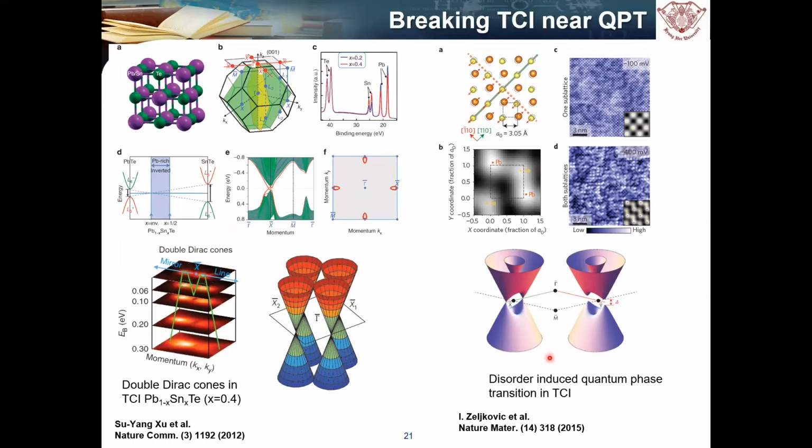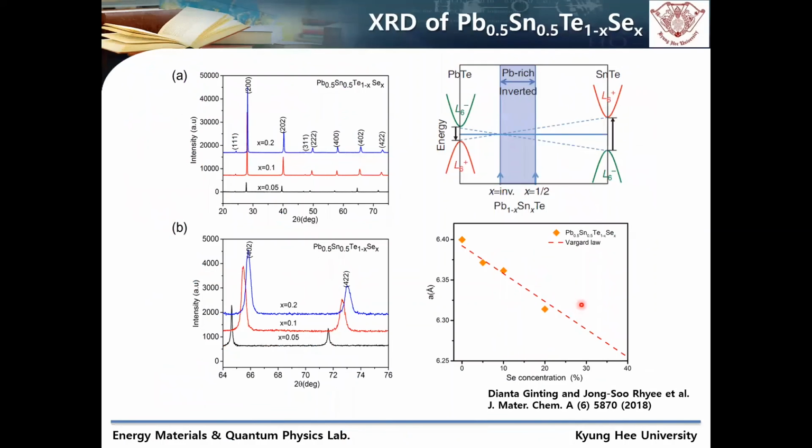But in this case, with completely symmetric electrons in the whole band, it means almost zero Seebeck coefficient. Therefore, a finite energy band gap is needed, and in this case we consider the partial energy band gap opening on this side. We tried successfully, and the partial energy band gap opening can be possible in terms of quantum phase transition near the topological phase transition, and therefore the partial band gap opening increases thermoelectric properties.